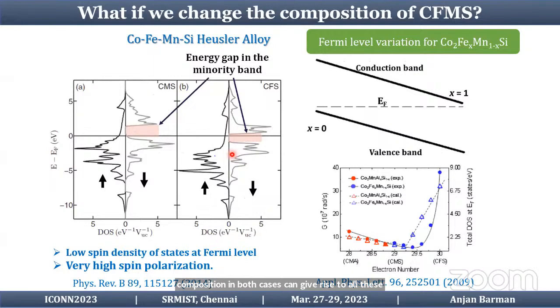The question is, what if we change the composition, and can we actually see the effect of Fermi level tuning in this case? So yes, this is the band structure of pure CMS, and this is the band structure of cobalt iron silicon. This is cobalt manganese silicon. Here you can see the Fermi level is close to the valence band. Here the Fermi level is close to the conduction band.